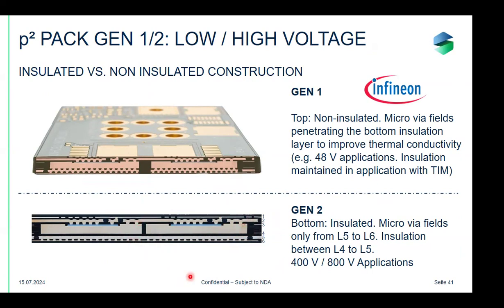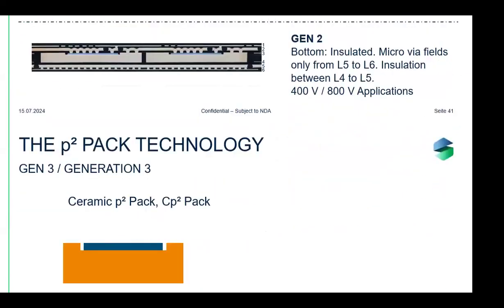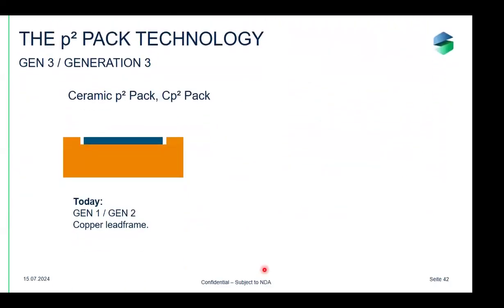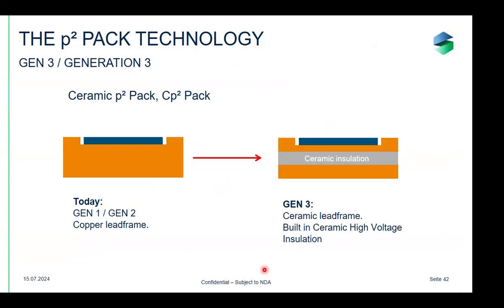But as we did not like this increase in thermal resistance against generation 1, we also thought about making kind of a combination of what we see in the market. If you look at power modules, they typically work with ceramic substrates. And therefore, in the past, they always had superior thermal resistances. And from their technology, we also learned that using a ceramic insulation could be useful for the embedding technology as well. And therefore, our generation 3 is using this kind of ceramic lead frame.